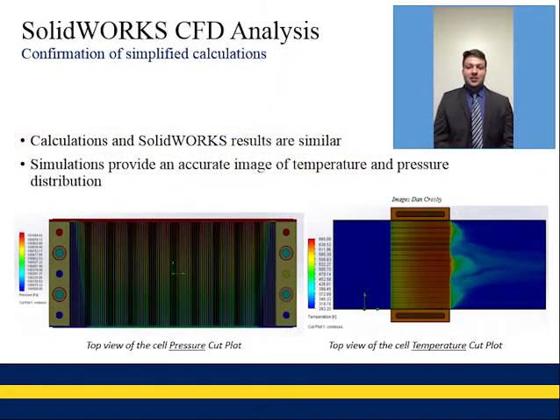After doing the calculations, we decided to run a few simulations to confirm our results. We ran a flow simulation through an individual cell, and we set the volumetric outlet flow to about 200 CFM, and we set an internal temperature of 90 degrees C. We also set the outlet pressure to be atmospheric.